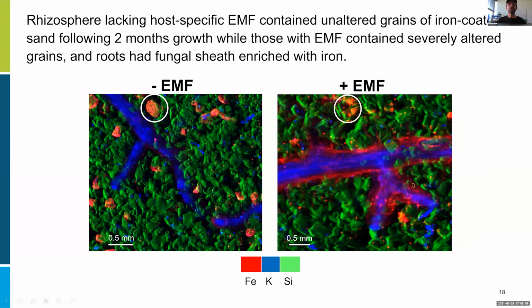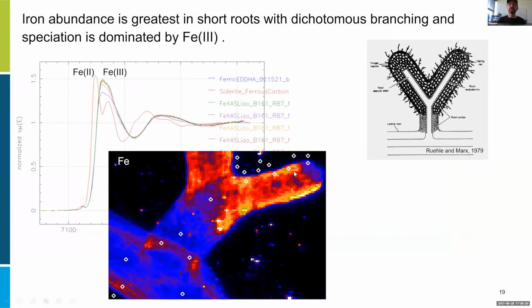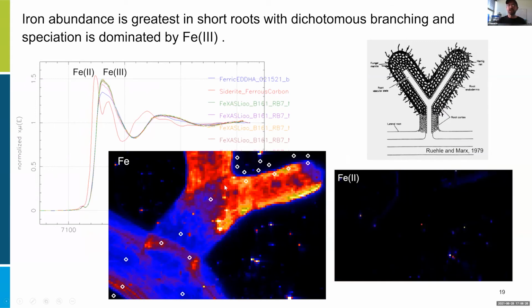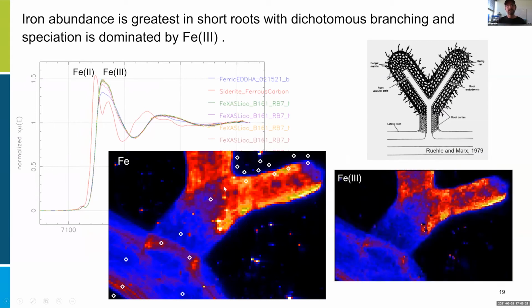After 2 months of growth in this system, they pretty much look like the way we put them into the system. But a couple months later, they disintegrate when you have the fungus in the system. And you can poke around these forked roots and look at the iron speciation and notice it's all iron 3, and that's not what we expected, but we've checked and checked and checked again, and it's all iron 3 everywhere we look, with one exception of the plant root itself.